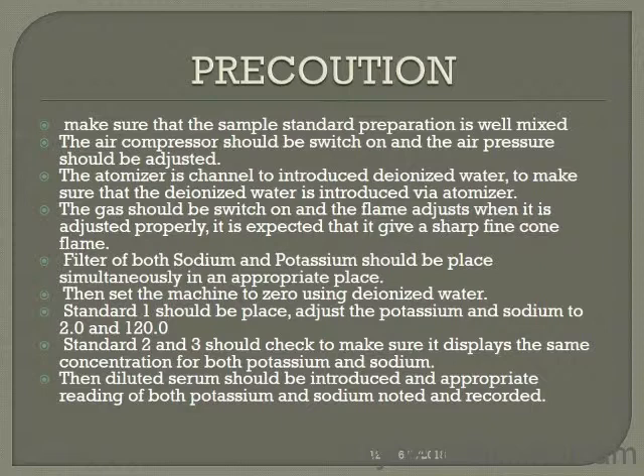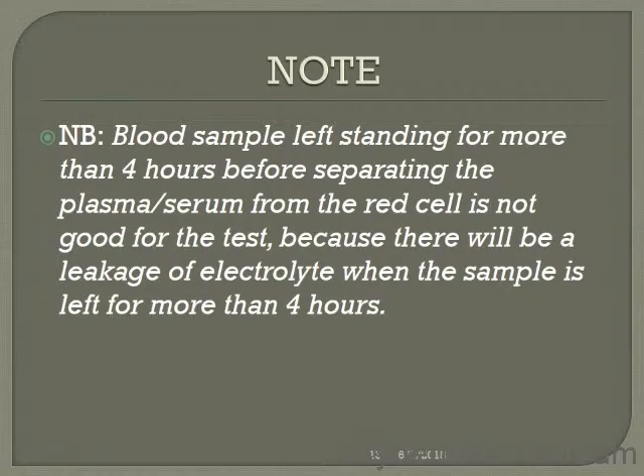The diluted serum should be introduced and the appropriate readings of both potassium and sodium noted and recorded. Note that a blood sample left standing for more than 4 hours is not suitable for this analysis. Never use any blood sample stored more than 4 hours, because there will be a leakage of electrolytes when the sample is left for more than 4 hours.